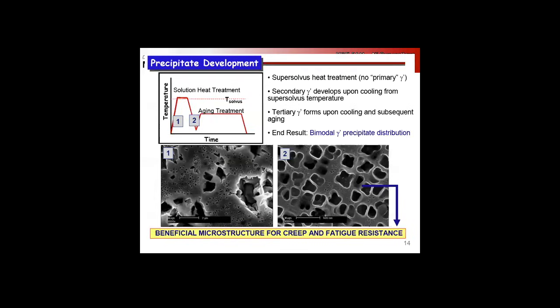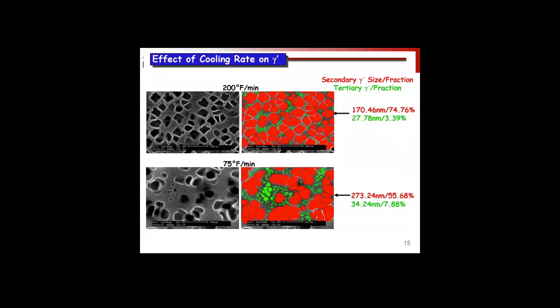So this is a blade alloy. Typically disc alloys will have a lower volume fraction, but the effective cooling rate is quite remarkable. Here we see cooling at 200 degrees - it's from industry, so it's Fahrenheit per minute, because that's frustrating - if you talk to GE or Pratt & Whitney or even Rolls-Royce, everything's in Fahrenheit. It's frustrating.